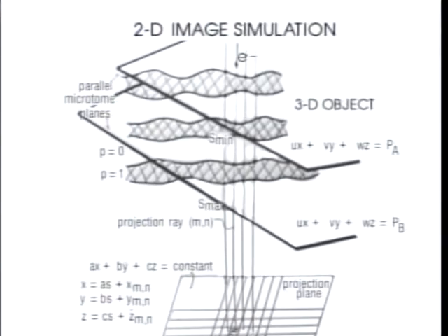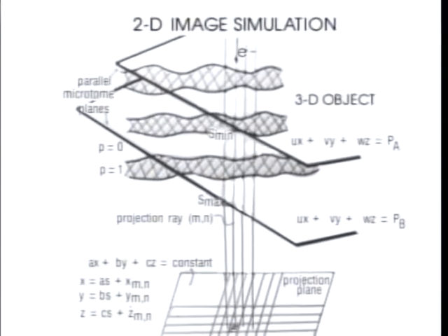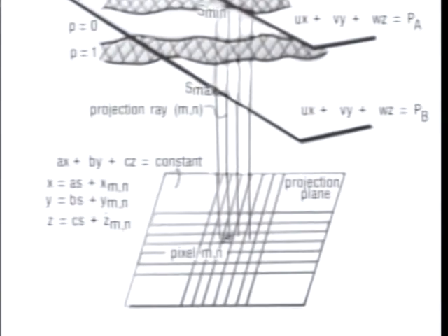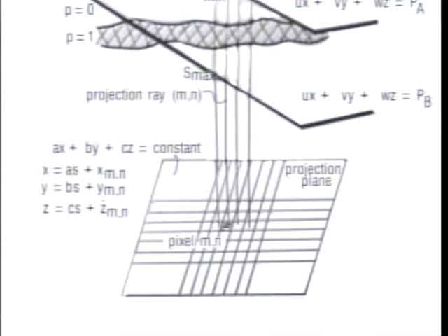First of all, one takes a thin slice of the material that might contain several periods of the conjectured structure. This is put under an electron microscope beam after one of the substances is doped to be somewhat opaque to the passage of electrons. A photographic film is then laid under the substance to register the beam, and one gets a grayscale image which is dark in the place where there's been a lot of occlusion of the electrons and light in the place where the electrons have passed quite freely. And by tilting the beam, one can get a sort of projective signature of the substance interface.